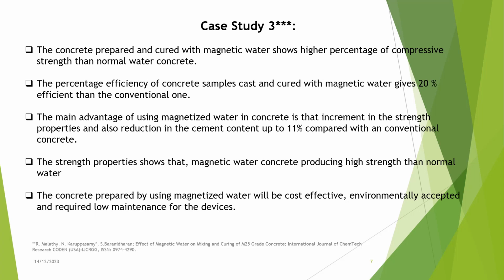Efficiency enhancement. The percentage efficiency of concrete samples cast and cured with magnetic water demonstrated a remarkable improvement, being 20% more efficient than conventional concrete. This efficiency gain highlights the positive influence of magnetized water on the overall performance of the concrete. Reduction in cement content. An essential advantage observed is the reduction in cement content by up to 11% compared to conventional concrete. This reduction not only contributes to the efficiency of the concrete but also aligns with the sustainable practice of minimizing resource use.